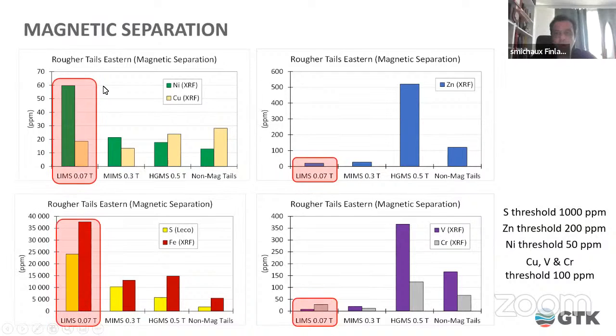So the low intensity magnetic separation fell into 7.4% of the actual mass. And we've managed to get below the threshold for some minerals, but when you actually sum everything up together, like the tailings that actually come out into the tails, we're still not quite there yet. So magnetic is helping, but it's not enough on its own.